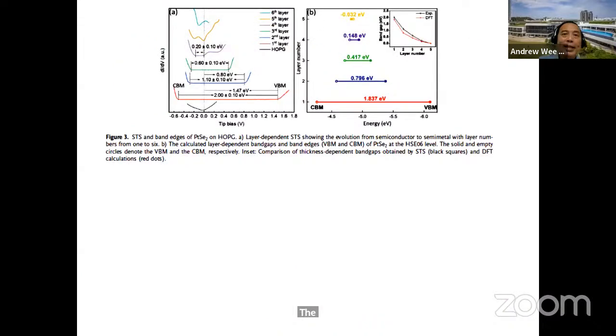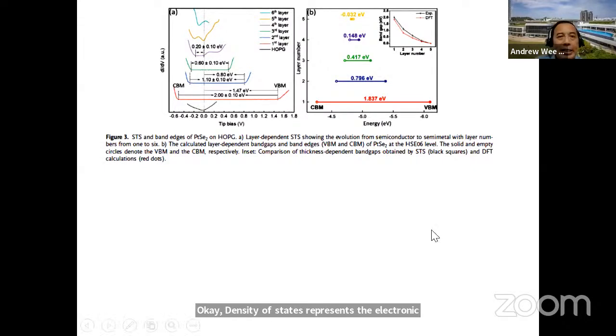Now, the interesting thing about STM is that if you do STS, scanning tunneling spectroscopy, that means you do an IV curve, you measure the current as a function of bias voltage, and you take the derivative dI over dV, you get the density of states. Density of states represents the electronic structure of the material. So by doing STS, this is dI/dV over V, you see that the first layer has the conduction band here, the valence band here, with a band gap of about 2 eV, and then the band gap decreases rapidly to 1.1 and then 0.6 and so on as the number of layers increases.